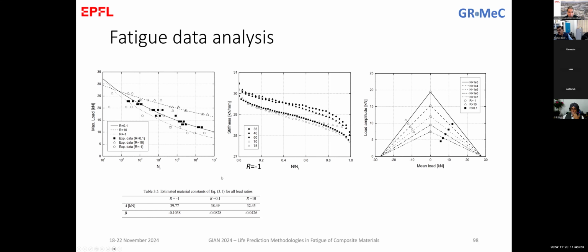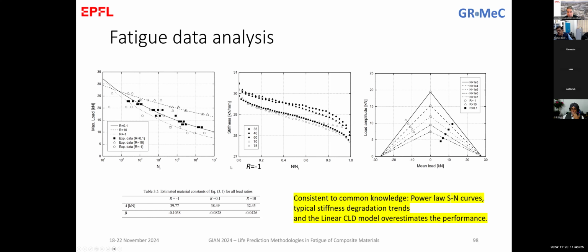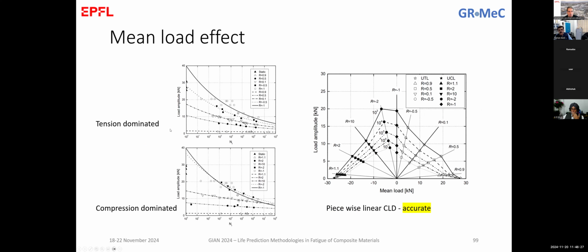And we have also the typical damage parameters here. So we perform more testing. I talk about a lot of testing for mean load effects. We created actually how many? 3, 6, 9 SN curves at different loading conditions, and established this piecewise linear constant life diagram, which is of course accurate because it uses all the fatigue data.